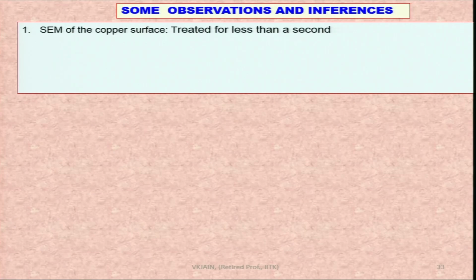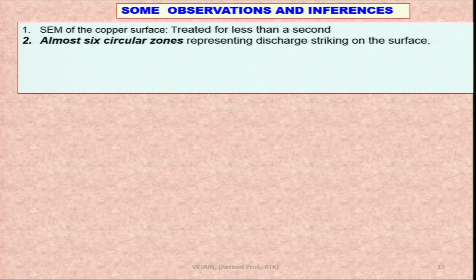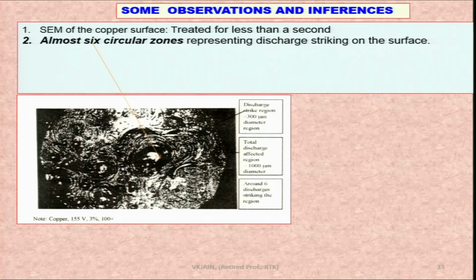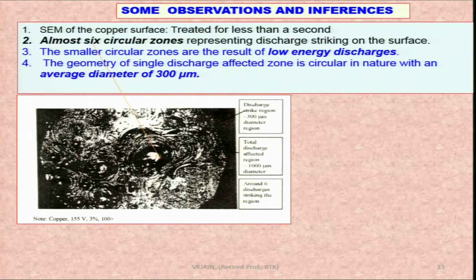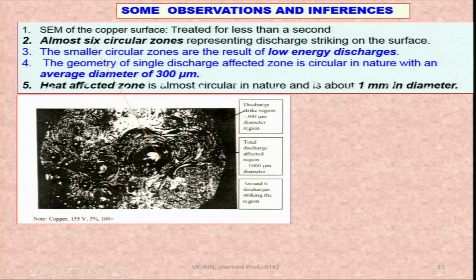Some observations and inferences. In the SEM of the copper surface treated for less than a second, almost 6 circular zones representing discharge striking on the surface were observed, as you can see here. The geometry of a single discharge affected zone is circular in nature with an average diameter of 300 micrometer. You can see over here. The heat affected zone is almost circular in nature, and it is about 1 millimeter in diameter.